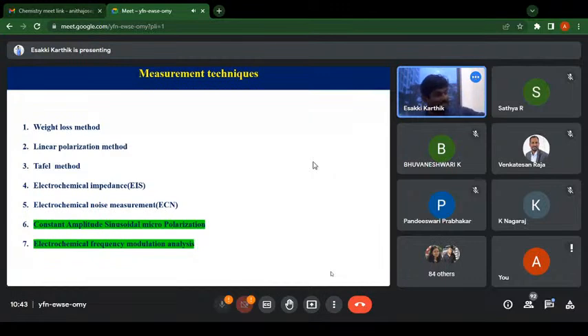You have to keep that iron rod for some time, maybe 1 week or 2 weeks. After that, whatever corrosion product is forming, you have to remove it. Before keeping it in that NaCl medium, you have to measure the weight. After keeping it in the NaCl medium and removing the corrosion layer, you have to measure the weight again. How much weight loss is there? Based on that, you can measure it.